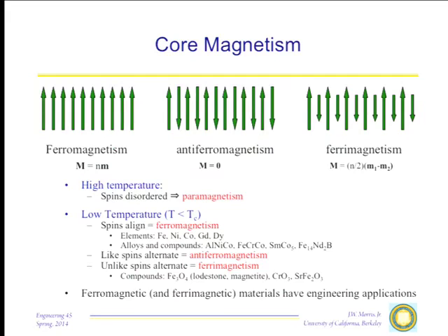And it turns out that almost everything in the periodic table prefers an antiferromagnetic ordering. That's why chromium and manganese in the metallic state are not ferromagnetic. They have big magnetic moments, but they're aligned in opposite directions, so there's no net magnetic moment. However, there's a third kind of magnetism, which is what we call ferrimagnetism. That is a case in which we have not a single material, but rather a material in which there's more than one magnetic moment or more than one state that can be occupied.